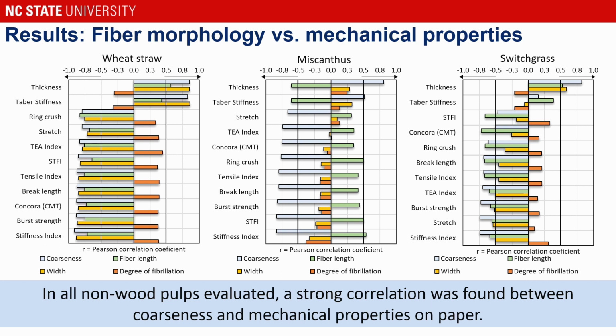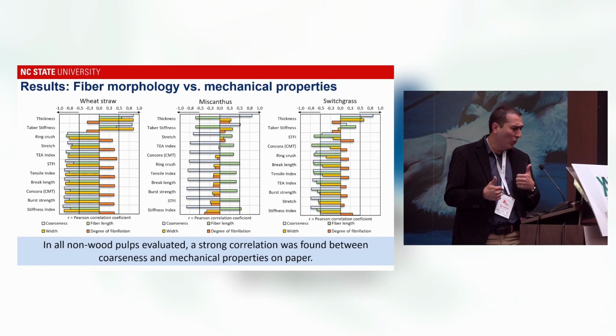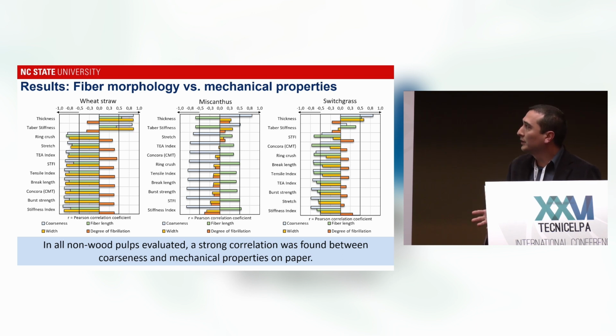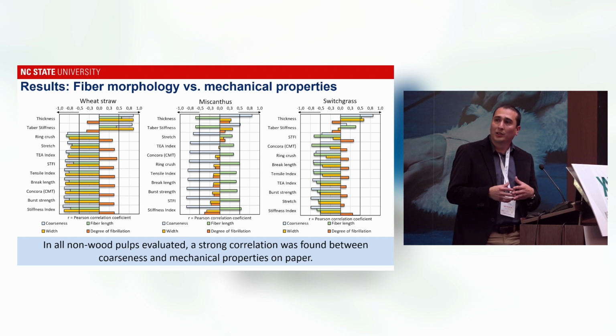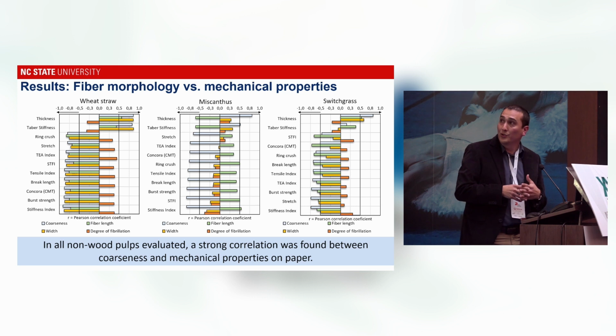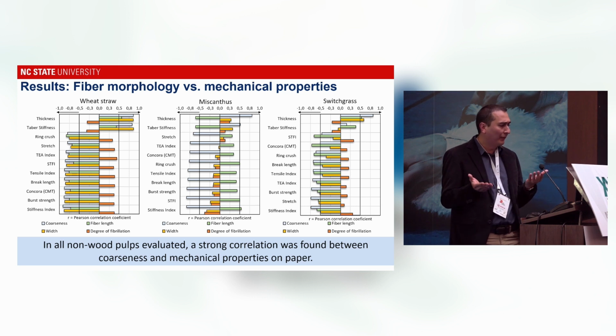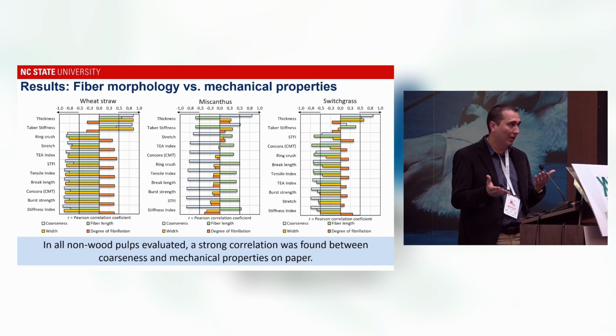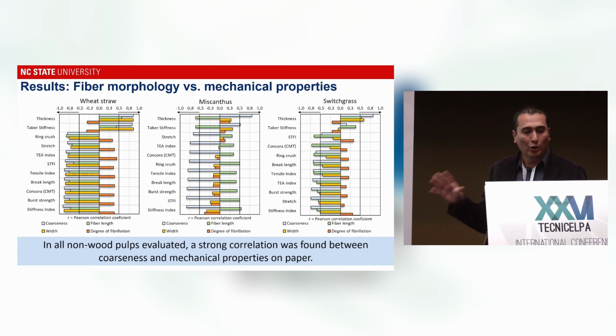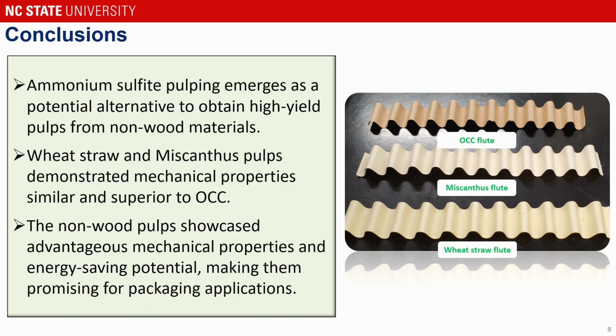So finally, we did morphology analysis, and we realized that, for example, when we compare the coarseness value, which is a common measurement for fibers, there is a good correlation between several mechanical properties and the coarseness value. This is important because, depending on the coarseness of those pulps, we can estimate how those properties are going to perform on paper. So as a conclusion, we believe that by using ammonium sulfite to process these non-wood materials, there is a potential to be used in packaging, at least in container board application. Thank you so much.